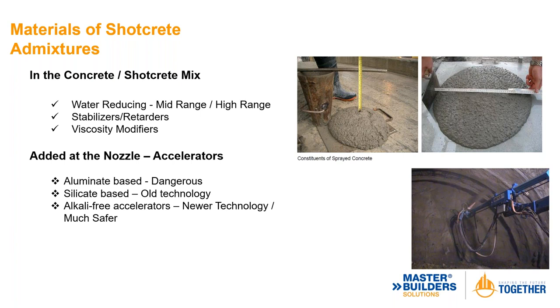At the nozzle, accelerators are added. A bit of history: aluminate-based accelerators used to exist — very dangerous, burning on contact — and are essentially outlawed in Canada and rarely seen in the US. Silicate-based accelerators are older technology (sodium silicate) still used in some mines and tunnels. But the number one accelerator choice is the alkali-free accelerator — it's much safer, and newer alkali-free technologies have been developed within that realm over the last 20 years.